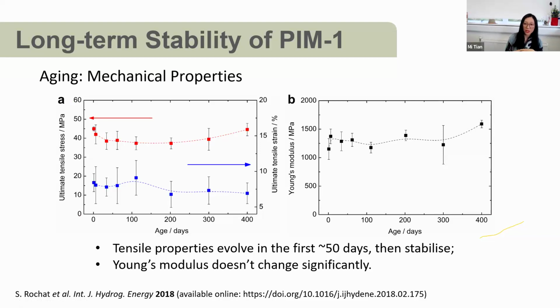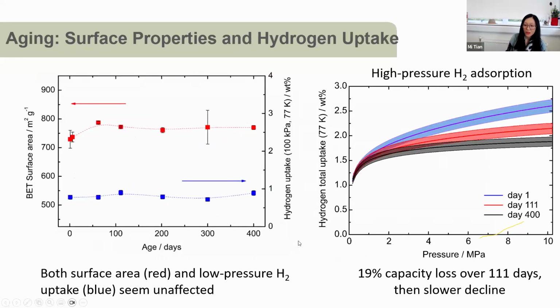So to evaluate the aging properties of polymer, we keep the materials in the same condition over time, and we measured its mechanical and different properties, and we found the mechanical properties evolve in the first 50 days and then stabilize. Young's modulus doesn't change significantly. Surface area and the low pressure hydrogen uptake keep stable, which seems unaffected by aging or by time. But the high pressure capacity loses over 100 days and then slowly declines.